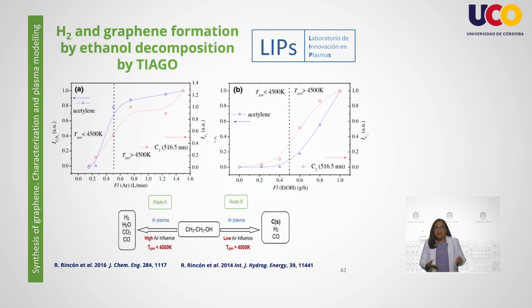Now, the gas temperature is also calculated through the optical emission spectroscopy analysis. On the other hand, the presence of acetylene and other gases is confirmed through mass spectroscopy. You can see on the plots the carbon and acetylene species formation during high and low air influence. Here we represent them as the A and B routes, respectively. And as a conclusion of this process characterization technique, the B route, with gas temperatures higher than 4,500 Kelvin, is more effective for the graphene synthesis, with the formation of hydrogen as a byproduct and without the formation of CO2, and therefore this ensures a clean process.